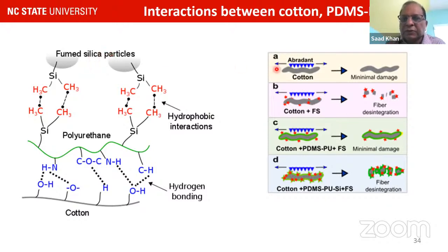But what is happening when we are doing abrasion? If you do pure cotton, the abrasion just destroys the cotton. When you have fumed silica, you have too many rough fumed silica particles, which, when the abrader is going, kind of disintegrates the cotton because it's rubbing against the fumed silica. And even a fumed silica coating seems to be not as desirable, but when we have PDMS, PU all together as part of the formulation, that becomes a nicer coating on the fabric, and then we see minimal damage, and this is the one that can show the most abrasion resistance.